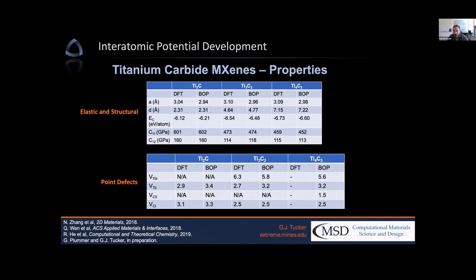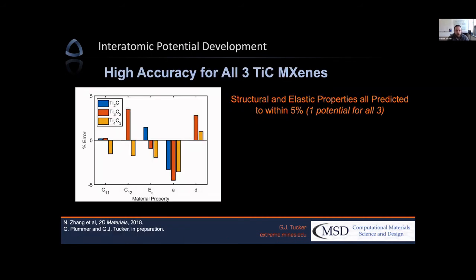So we're fairly confident, at least in regard to the available data we have from published literature, that this bond order potential does a good job for this titanium carbon system, and for all three stoichiometries. If we look at an overview schematic of this new potential, it has high accuracy for all of them. As shown here, we have the percent error on the vertical axis and various material properties on the horizontal axis. Both these structural and elastic properties are all predicted to be within about 5% of the target values we get from density functional theory. Just to reiterate, this is one potential for all three systems. It's not one potential for each; we have one potential that actually does all of them, and that's a very hard thing to do.